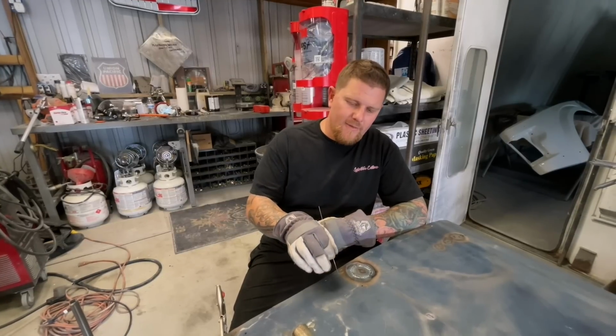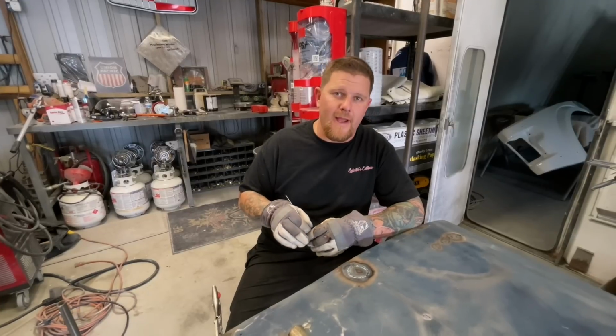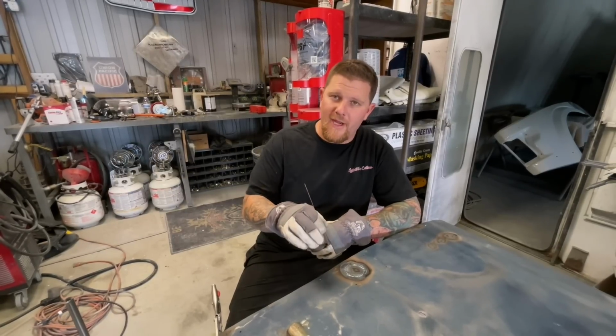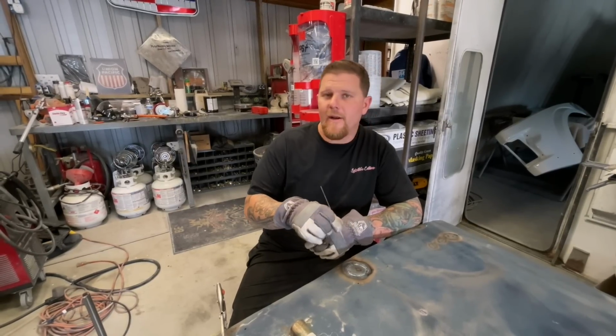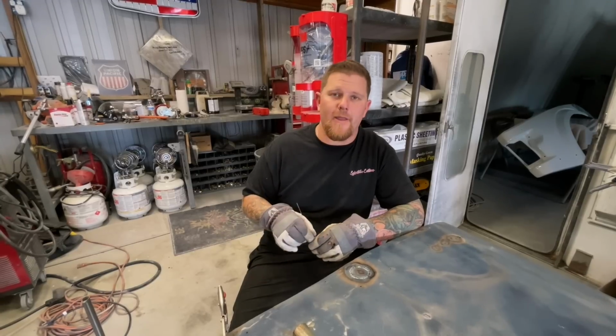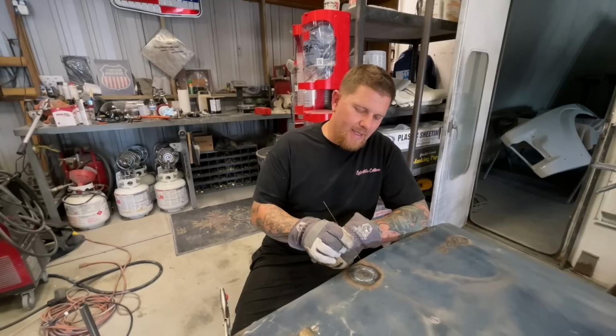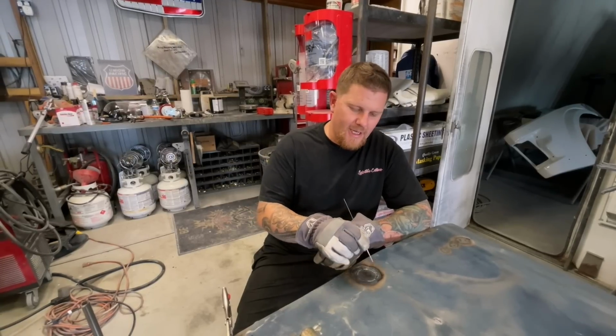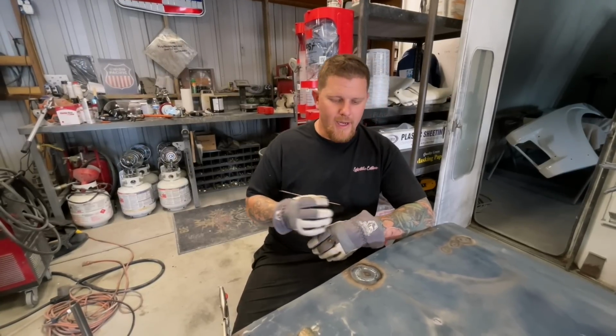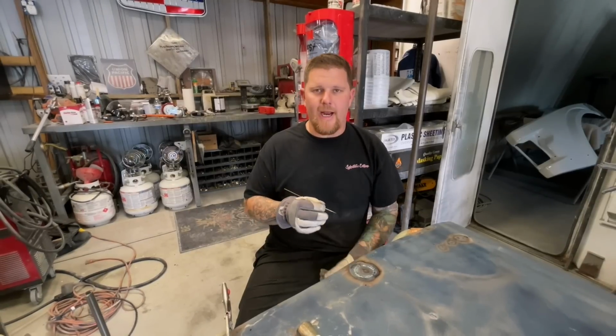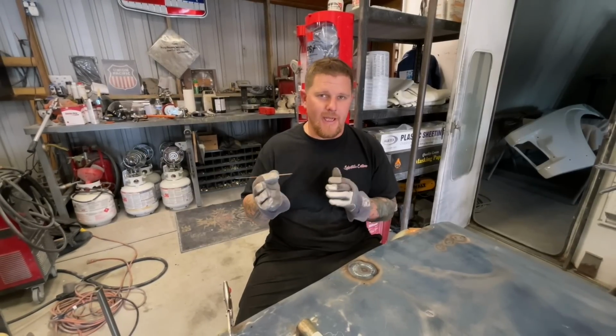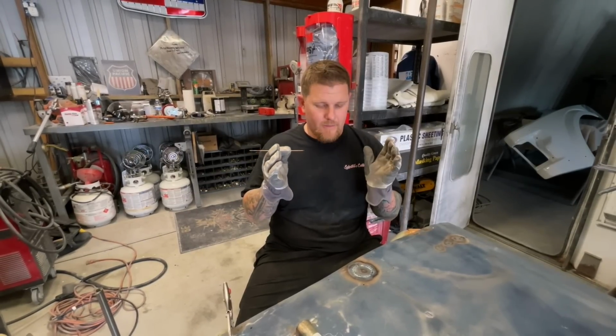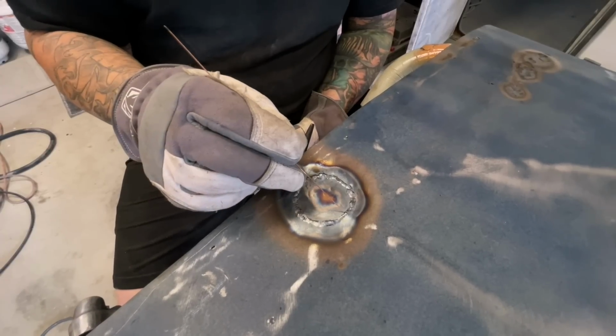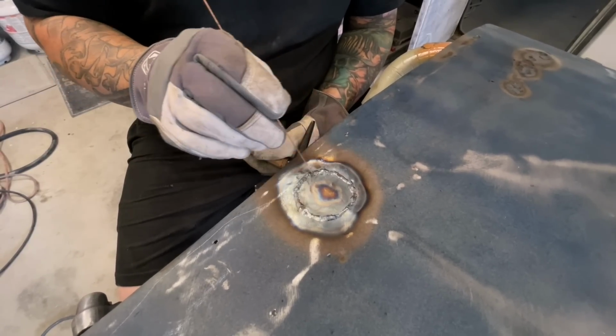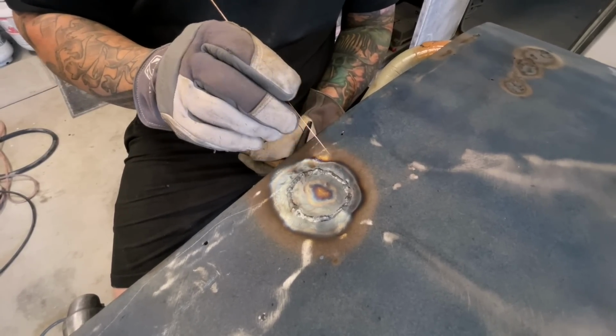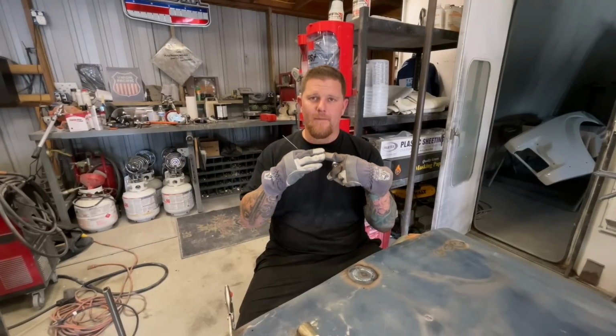So even though this is around 43 to 45 thousandths of an inch on the sheet metal thickness, we ended up liking around 28 amps on the actual TIG welder, and it made a big difference on one side versus the other, just welding up this small hole. It keeps your warpage down, and when you look at it, you can see one side versus the other that one has a little bit less warpage and one has a little bit more warpage. Not that that's a big, huge deal, because we're gonna hammer and dolly it out and bring up that shrink that happened.